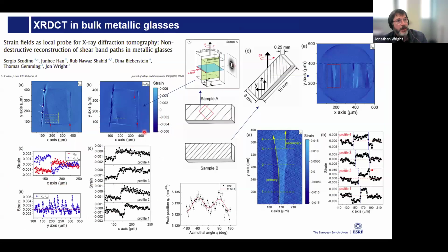The same idea of doing XRD-CT on glass this time was for strain extraction. This was with Sergio Scudino and the shear bands that he finds in glasses. So in this case, we fit the position of the diffraction ring around the circle, and the strain tensor component that's parallel to the rotation axis can be reconstructed.